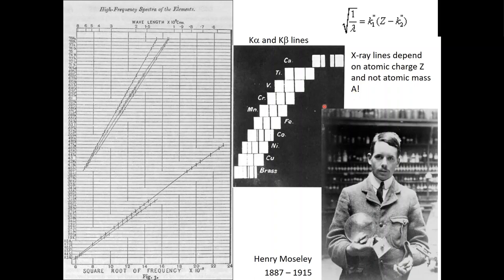But this was not leading to the final conclusions and the final periodic table that we have now. So a technique was required that is sensitive to the atomic charge. And X-ray K-alpha lines, K-beta lines, so the fluorescence lines, or X-ray emission lines, are sensitive. The energies, this is shown here, relate of course to the wavelength, and depend on the atomic charge. So that was very important.